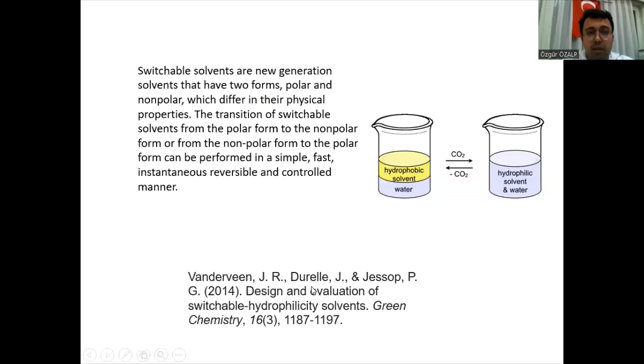And you can see this figure contains two forms: the hydrophobic solvent and water. When the switchable reaction starts, it is hydrophobic and then converts to a hydrophilic solvent. If you do not use carbon dioxide, this reaction does not complete. The polar form, non-polar form, this one. And lastly, you can obtain the hydrophilic solvent. The switchable solvent method is simple, fast, and reversible. And most important, it is controllable.